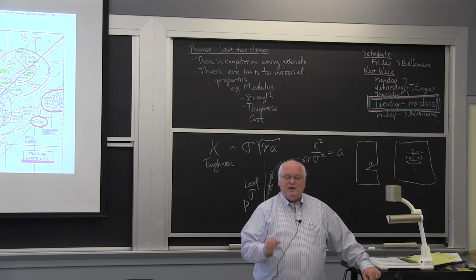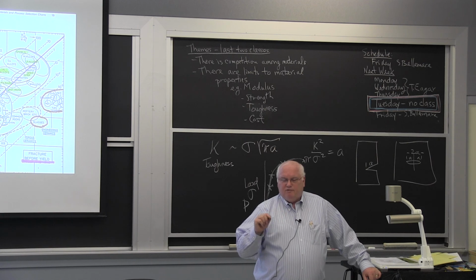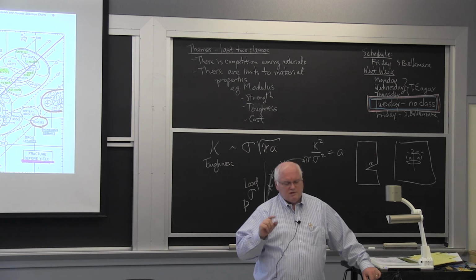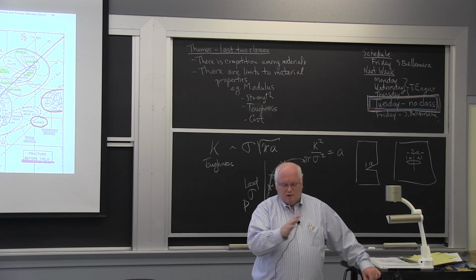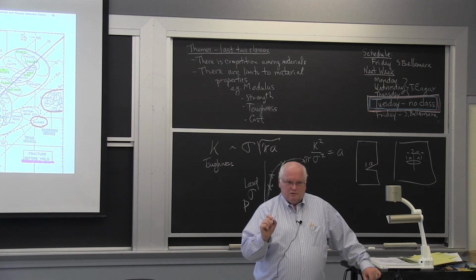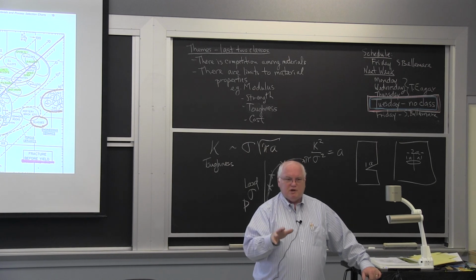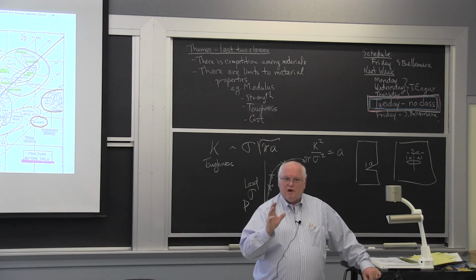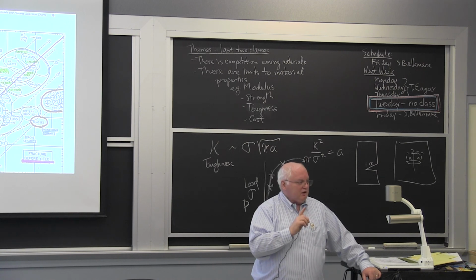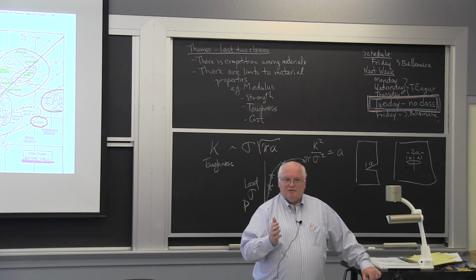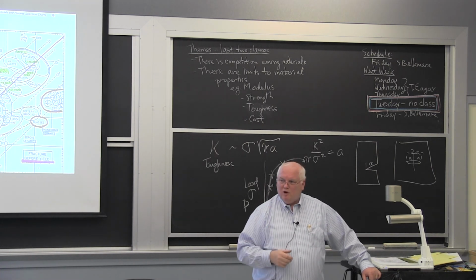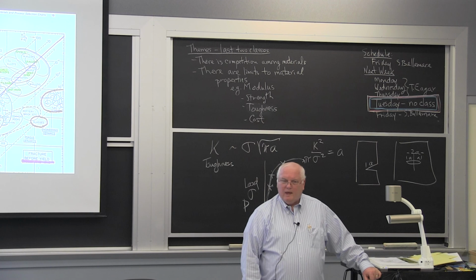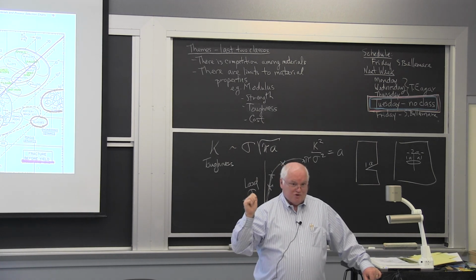So we redesigned it to 7075-T651, I think, or no, T6, no, T7. Anyway, I have to go back and look. But I looked up the properties. We had to make it a little thicker, okay, because we had lost strength. But the critical flaw size, the toughness, went up by a factor of 2, even though we only lost 10% in strength, because we got a doubling of toughness by the different heat treatment. And now we would have a leak before the thing shatters. Okay, so you might get sprayed with oil, but it doesn't blow up in his face. So that's leak before break as opposed to fracture before yield.